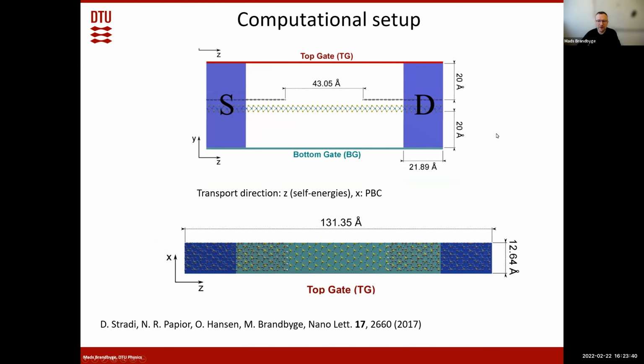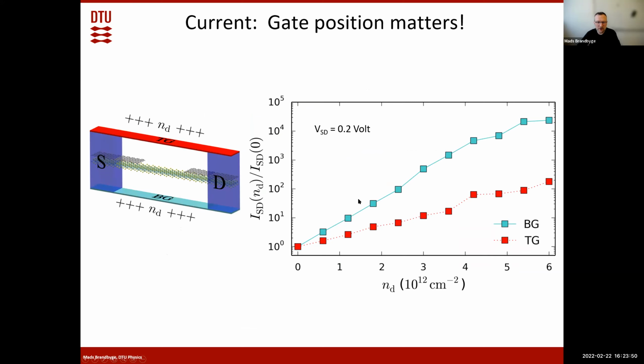This is the computational setup, just to show you the size of the calculations we are doing. But this is the result. It shows the source-drain current as a function of the gate doping. So the gate charge, we are controlling the charge on the gate. That's like a gate voltage if you put in the capacity of the gate. What is striking here is that the current and the transconductance, so the slope in the current, is very different if you use a back gate and a top gate. So you get a much more responsive transistor if you use the back gate here. And why is that?